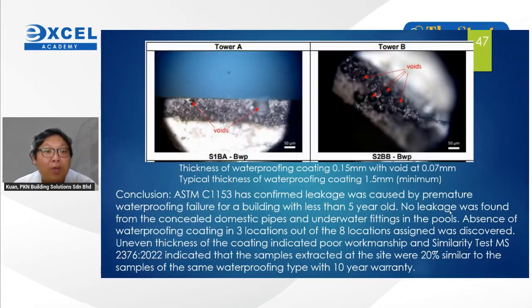Okay, Tower A. The thickness of the waterproof is 0.15 mm, and the typical thickness of waterproofing coating of the same family is minimum 1.5 mm. So it only has 10% of the required thickness. Okay, and out of this 0.15 mm, 0.07 mm were the voids.